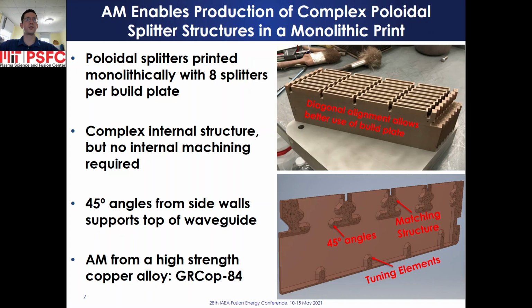The complex combination of tuning elements within the traveling wave power divider and integrated aperture matching elements are enabled by use of additive manufacturing. Power splitters are printed monolithically with 8 splitters per build plate. While the internal structure is complex, no internal machining is required. Internal supports are eliminated by printing 45-degree angles from the sidewall supporting the top waveguide surfaces. These angled structures have little effect on the RF properties of the divider. By using additive manufacturing, a high-strength copper alloy, GRCop-84, is able to be utilized to withstand disruption loads.